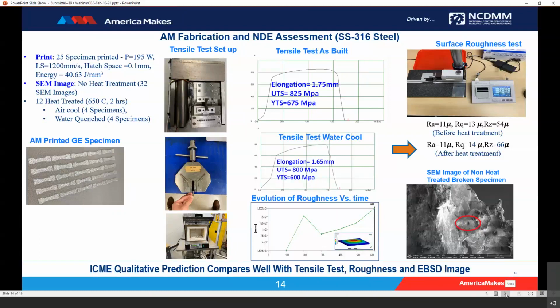In the lower left, you can see that even roughness varied with time. The measurements for surface roughness were indicated for before heat treatment and after heat treatment, and we also use scanning electron microscopy wherever possible to show the non-heat treated items, and in this case, the circle indicates a precipitate in that overall structure. Ultimately, we can say ICME qualitative prediction compares well with test for roughness and EBSD imaging.